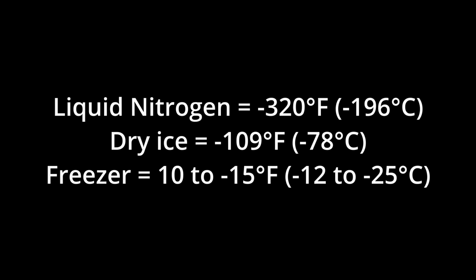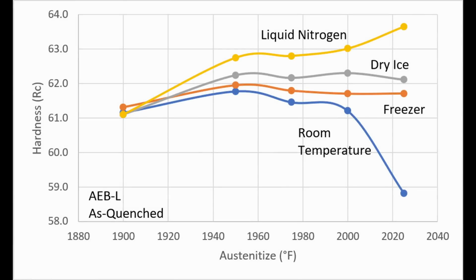I have also tested the use of household freezers, which are in the range of like 10 to negative 15 Fahrenheit or negative 12 to negative 25 Celsius. This is not as effective since it isn't as cold. The lower the temperature, the more effective the cold treatment is, though even a freezer can affect the transformation of the steel.